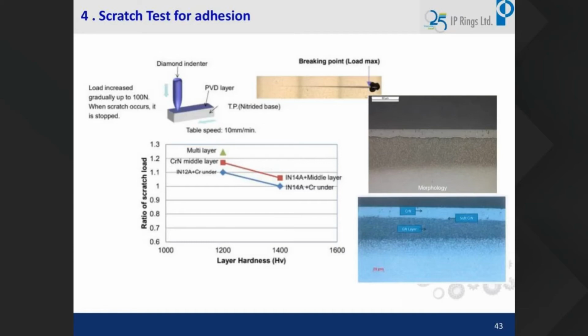So when we subsequently analyzed the product, what we found is that this particular chromium interlayer was not supporting. What our collaborator recommended is that we change it, and instead of this chromium interlayer, we used one more middle layer, what we call a chromium nitride middle layer. And here the adhesion is claimed to be better when compared to the chromium interlayer. With the soft chromium nitride middle layer, the adhesion is very much intact.